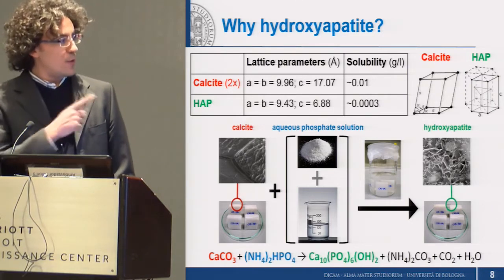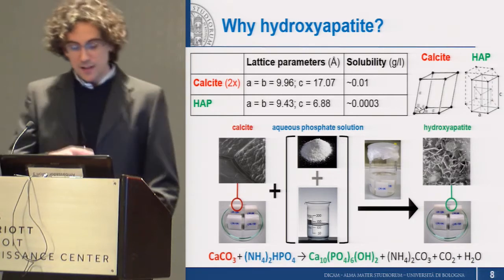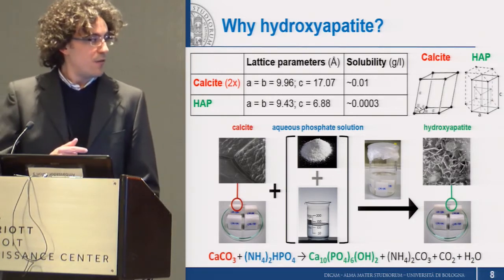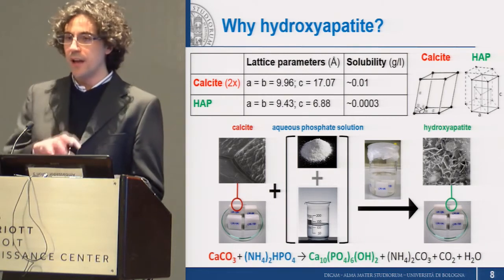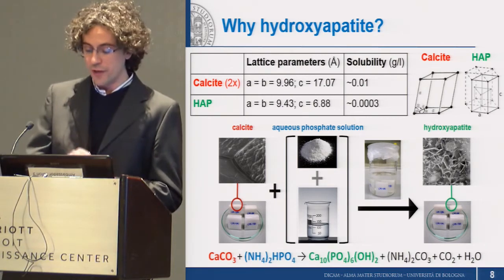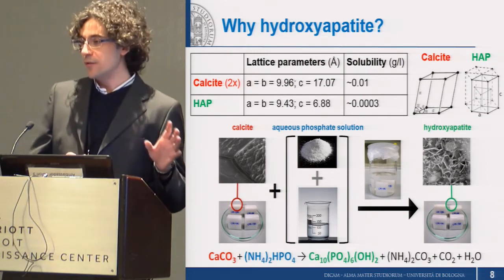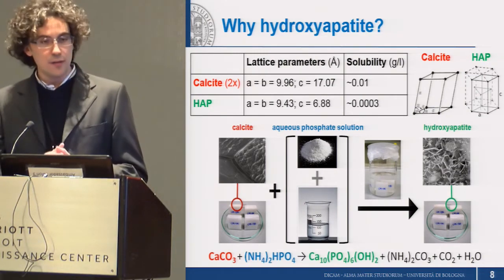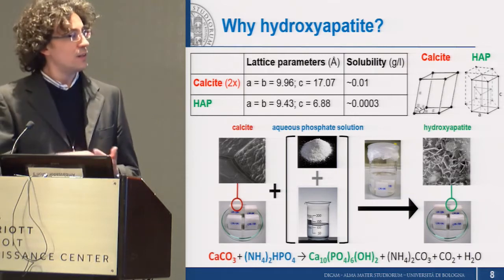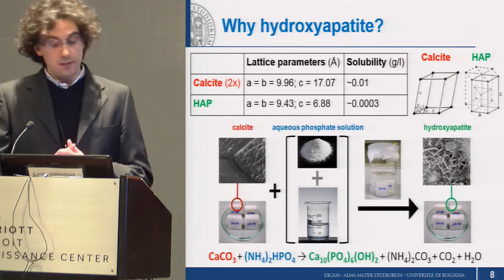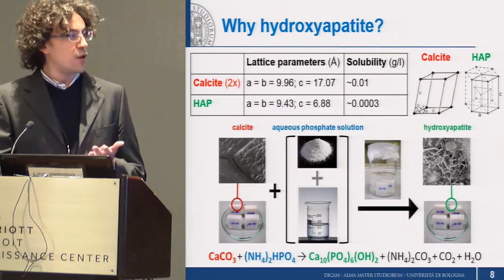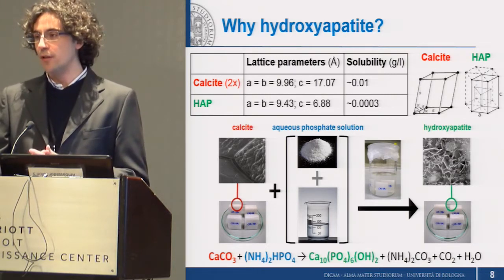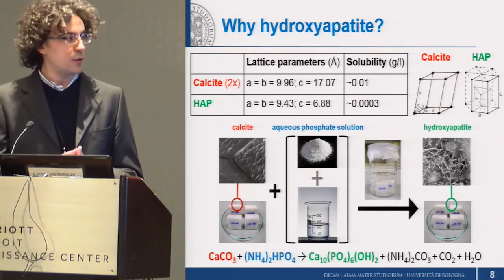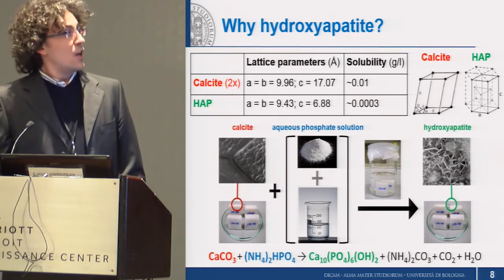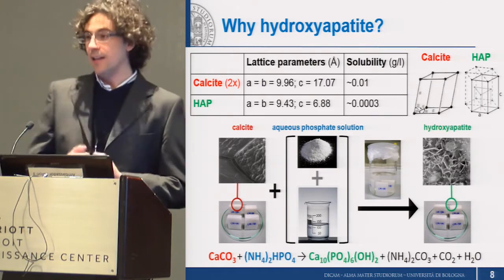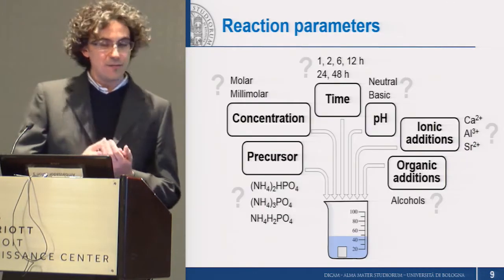So it is possible to form hydroxyapatite, in green, starting from calcite, calcium carbonate, by reacting calcium carbonate with an aqueous solution of a phosphate salt, so that in the end the calcium ions come from the substrate and the phosphate ions come from the solution that we treat the stone with. And what is formed is, in theory, stoichiometric hydroxyapatite and some volatile byproducts that do not remain in the stone and so aren't harmful.